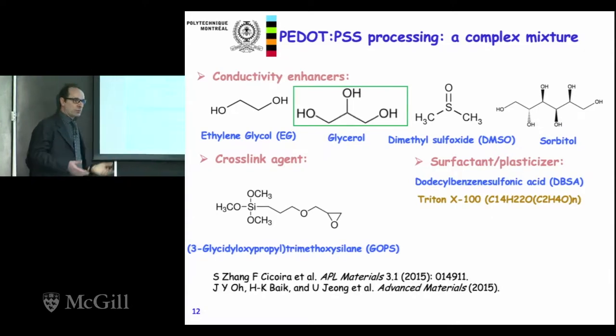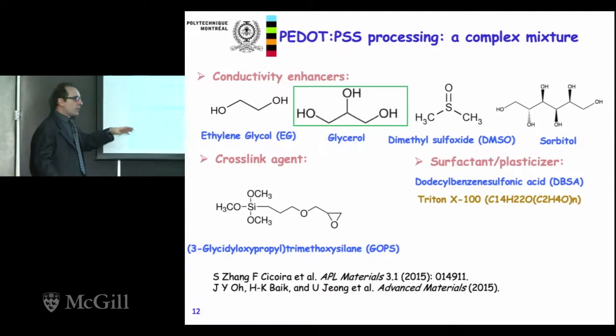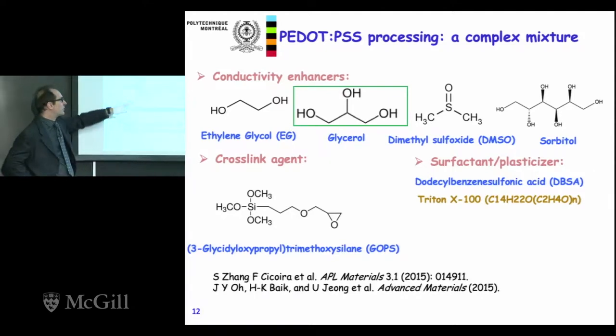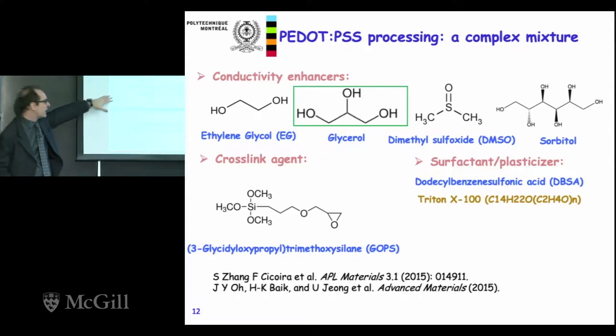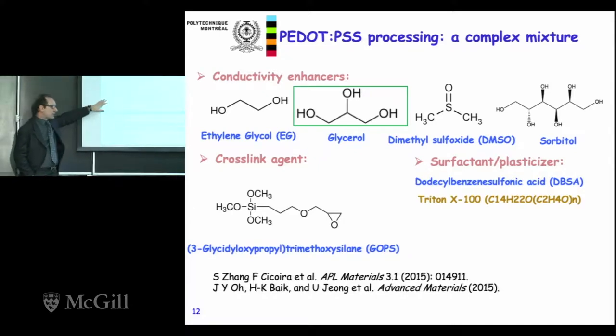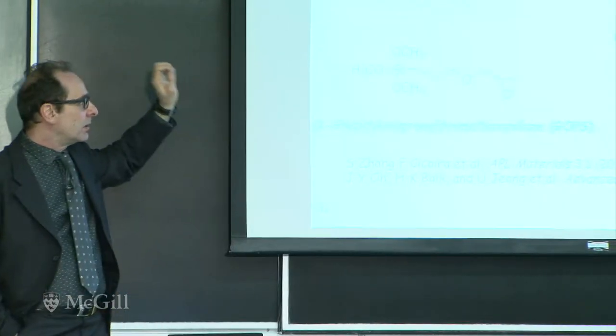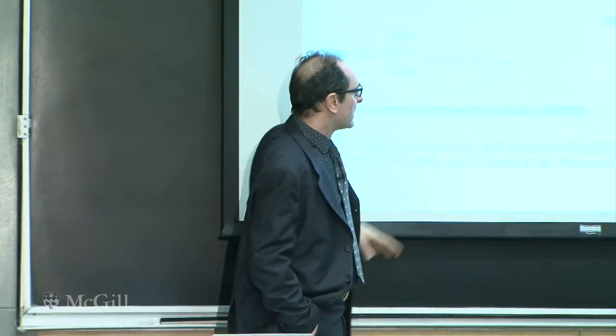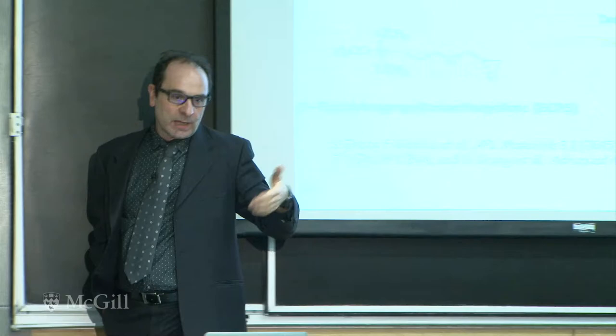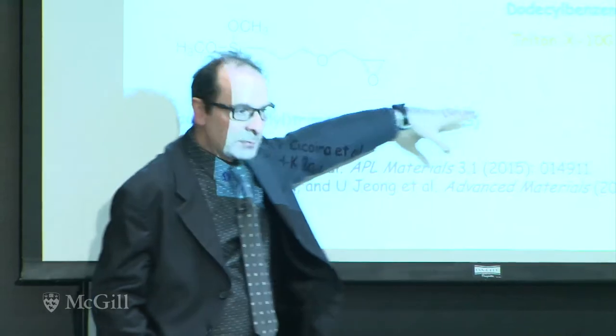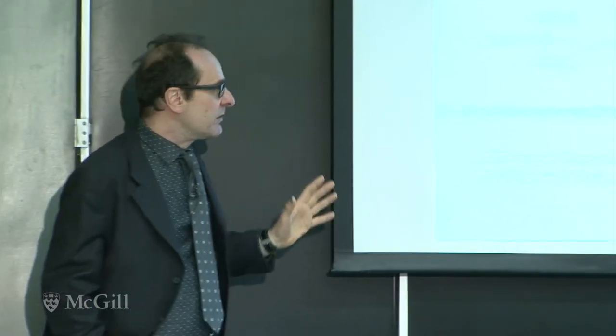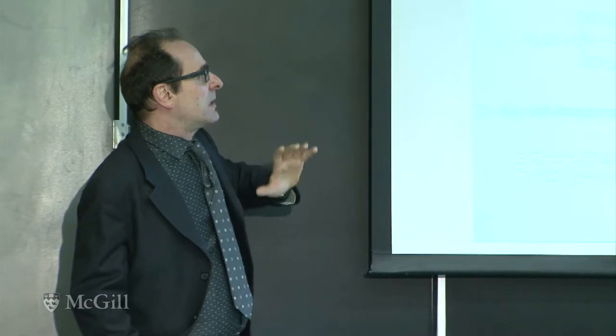Then sometimes you have adhesion problems of the films to a substrate. Then one method to improve the adhesion is to use a silane-based chemistry, so cross-linking with silane species. And this has been shown to improve the adhesion of conducting polymers, especially on inorganic substrates. And then if you want to make flexible or stretchable devices, you need to add surfactants to the films. Again, the reasons are still not very clear, but you have to do this if you want to work with a flexible or a stretchable substrate. So this is just to give you the idea that it's simple to process this material, but you have to find the right way to mix them with other components. So you have to play a lot with mixtures.